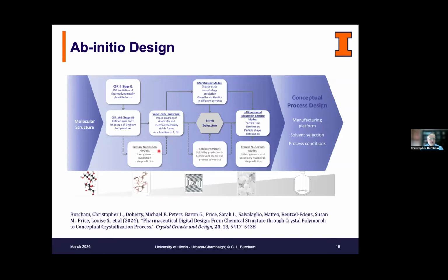And so we had a hypothesis that we need to understand primary nucleation, and we needed to be able to predict those homogeneous nucleation rates to determine, of those predicted low energy forms, which would be more likely to be observed experimentally. And once you had that, then you could start to develop the solid form landscape. You would understand what crystal form to carry forward. You could do morphology modeling and start to predict relative growth rates of the different phases in different solvents. You could do solubility modeling and end up then with the ability to do a multidimensional population balance model and get an idea at least of what that development process might look like and how easy or difficult it might be to control the desired solid state properties of your active ingredient.